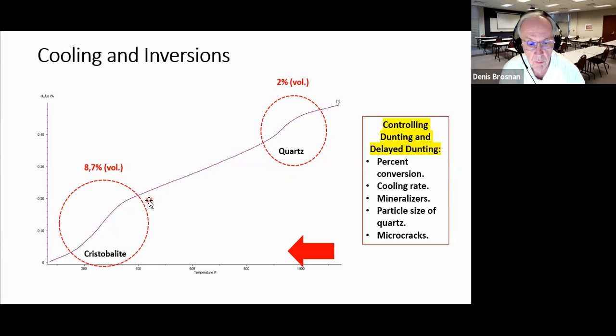Now, if we did form some cristobalite, or if we only have cristobalite there, then we're also going to go through a beta cristobalite to alpha cristobalite inversion on cooling, at an 8.7 volume percent decrease. And you can see that's a little bit more decrease right there on this dilatometer curve. And here we have to be very aware of this, because cristobalite inversion is primarily blamed in technical literature for dunting or cracking of ceramic ware in cooling in kilns.